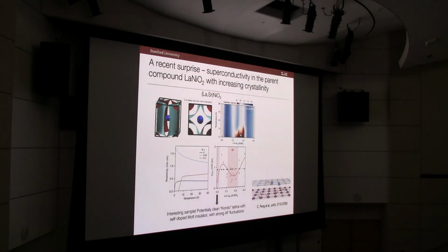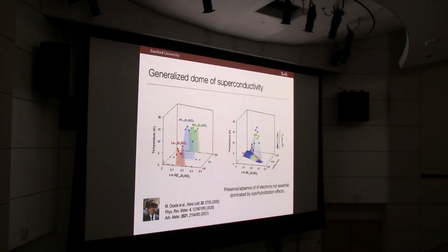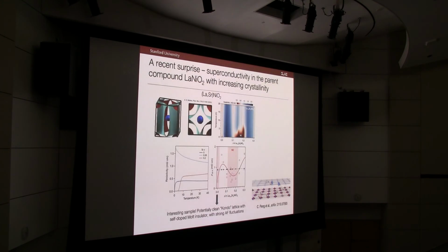Now, a recent surprise that has got us pretty excited is that we find superconductivity even in the parent compound, in the case of lanthanum nickel O2, with increasing crystallinity. Just to go back here, if your eyes were careful, you might have noticed this little glitch over here and here. It does seem to be real.